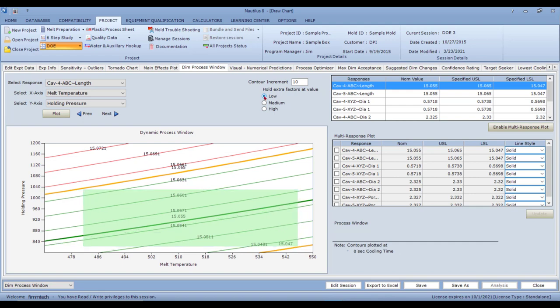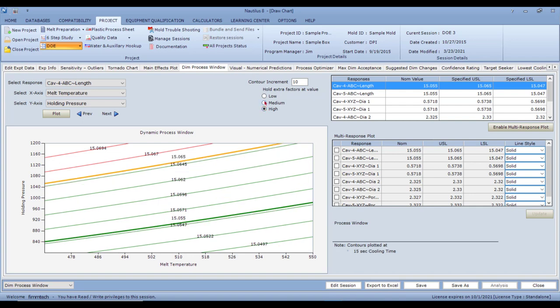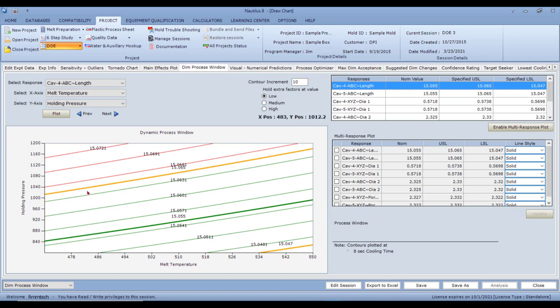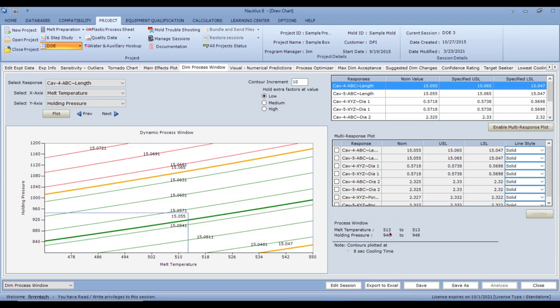The third factor is held at center, but you can change it to low. We know from the tornado chart that cooling time doesn't affect this dimension much — the contours barely change. But let's say I want to run at the fastest cooling time of eight seconds: I can draw the dimensional process window and select the most robust area. In this case, a temperature of 515°F, holding pressure of 950 PSI, and cooling time of eight seconds gives a very robust process for length in cavity 4.